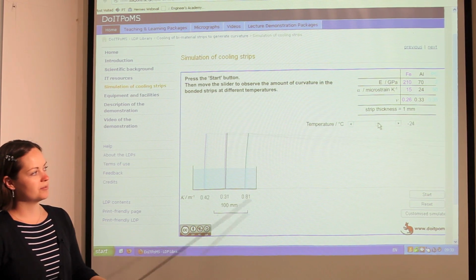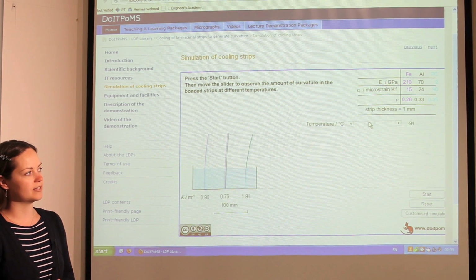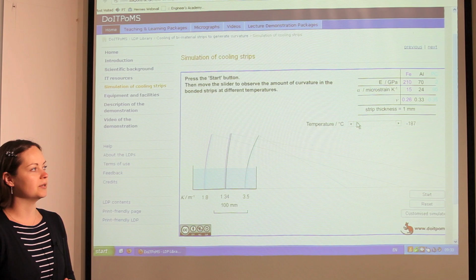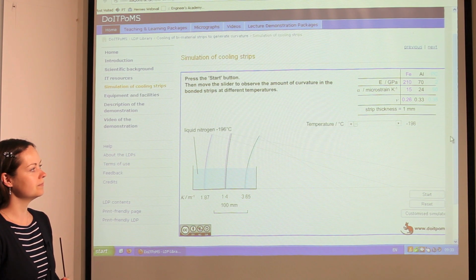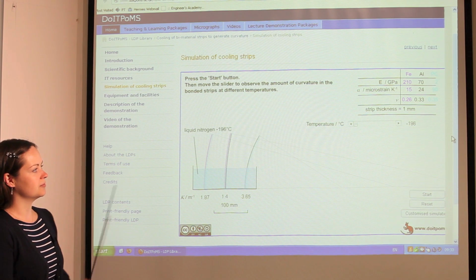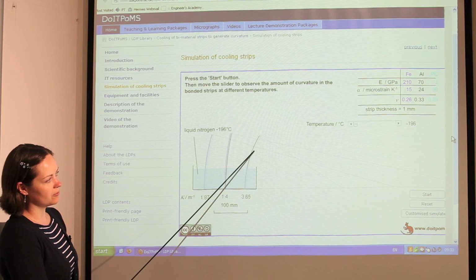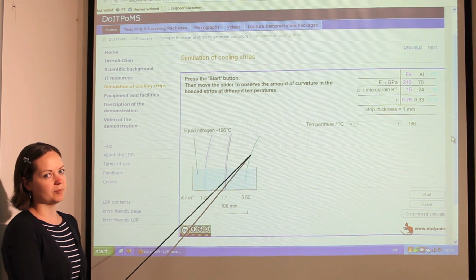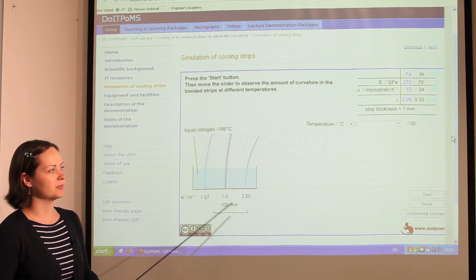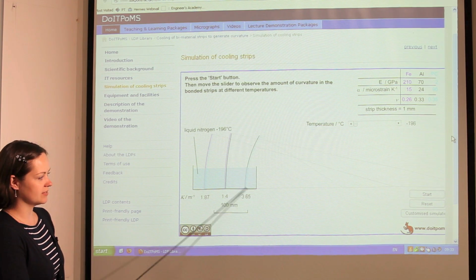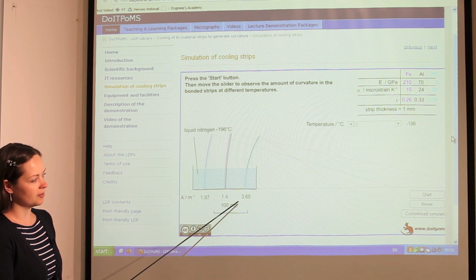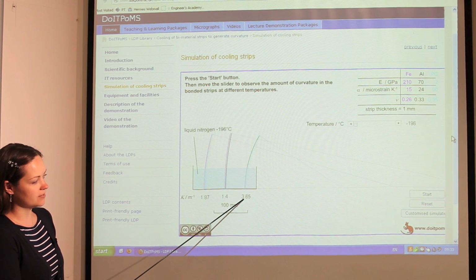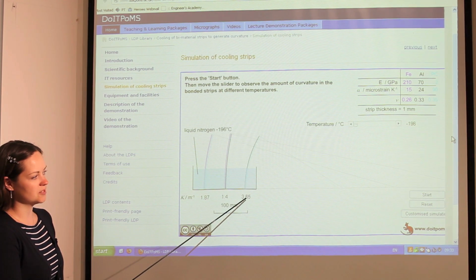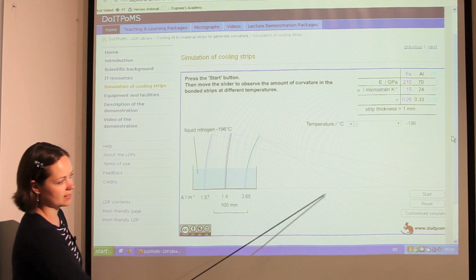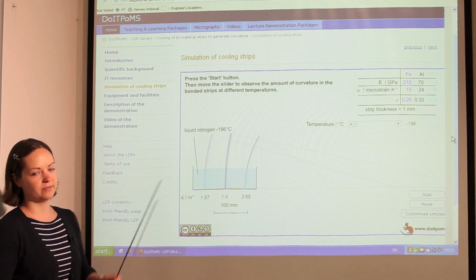So we're going to change the temperature down to minus 196 degrees C, or 77 Kelvin, which is the temperature of liquid nitrogen. So you can see that as we cool them down, the strips bend, and the strip with the greatest curvature is the aluminium polycarbonate strip, which is the same as in the experiment. So the curvatures are given down here, and for the aluminium polycarbonate strip, the curvature is 3.65, which corresponds to a radius of curvature, which is this distance here, of about 300 millimeters.